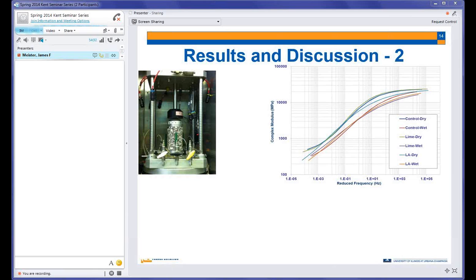But if we compare each mix's unconditioned state with its conditioned state, we can see there's a drop of the master curve. Now, it came to our knowledge that some researchers have used this test to check if it's able to capture the moisture susceptibility of asphalt mixes. And what did they do? They measured the complex modulus at 21C, and at each frequency at 21C, they found what we call the E-star ratio, in which they divided the E-star, or the complex modulus, of the conditioned relative to the unconditioned, which is similar to the idea of the TSR.